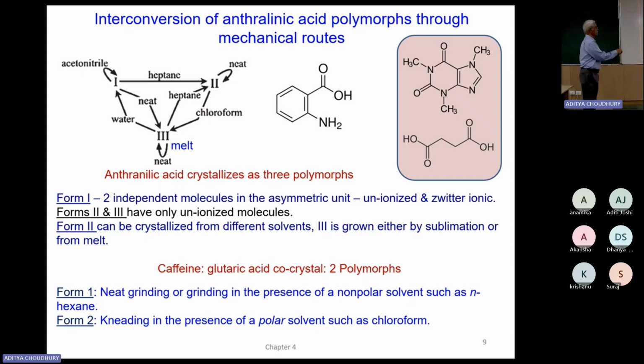According to them, if you take it and you melt it, you can also melt and recrystallize, so you get only form 3. Neat means you just grind them. There's no change. And here form 2, again, if you grind them without any solvent, it doesn't change. Whereas here in acetonitrile, it is present. But if you grind them neat, it goes to 3. Form 1 goes to form 3. Like that, you can interconvert. If you add a drop of heptane and then you grind it, you can convert from one form to another. That's quite interesting.